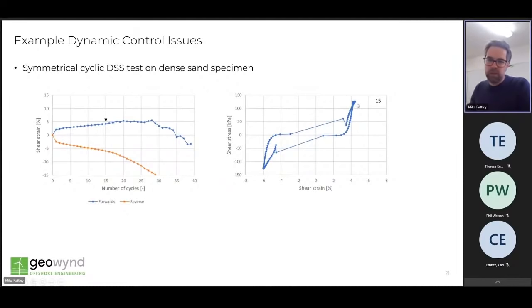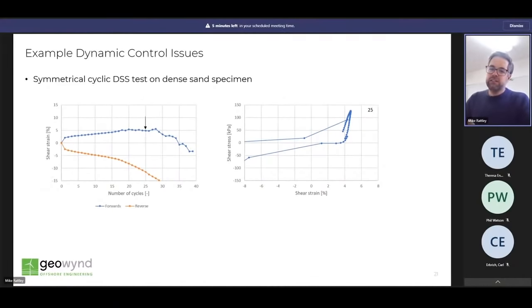So we see up here. After this point, the strains or the peak strains become progressively imbalanced, and we can see actually that we get a complete shift in the peak strains on the forward side, and the test essentially is out of control completely from this point. Reliable interpretation of this test is actually limited to quite a small number of cycles, and it's an important illustration of why the interpretation must be judged on a cycle by cycle basis.